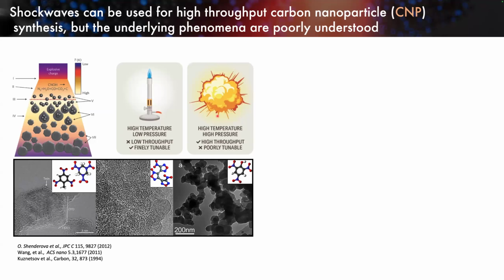In the case of an energetic or explosive precursor, what's happening is the detonation of the material imparts a shock wave into the material that drives it to the high temperature and pressure that causes the formation of these nanoparticles. What that pathway looks like is a function of the chemical nature of your explosive. So if you want to make some material other than these three, you're going to have to blow up a bunch of stuff until you find one that happens to make the particle you want.